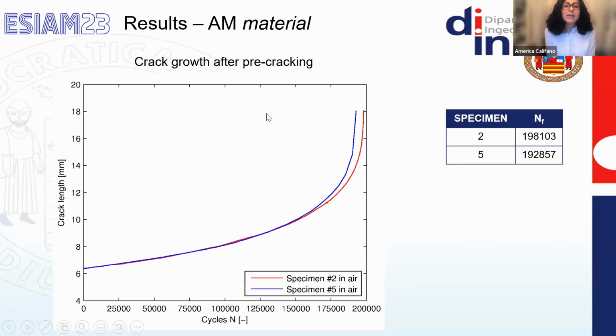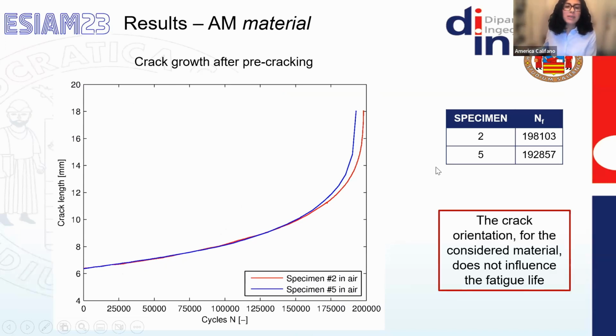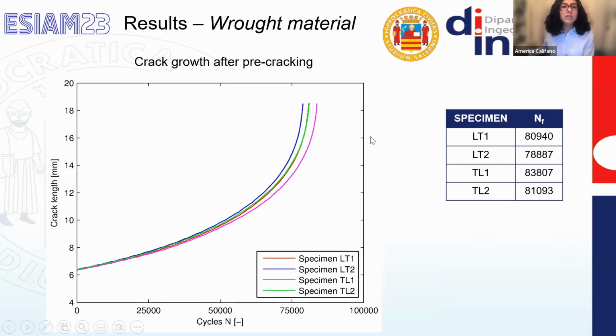At this point, we can take a look at the crack growth curves after pre-cracking for the 2 different sets of specimens. For the additively manufactured CT specimens shown in this slide, we can see that the 2 curves for specimen number 2 and number 5 are almost completely overlapping, and even in terms of the number of cycles to failure, the specimens share a similar behavior. So there is no influence in this case of the crack orientation on the fatigue life, and a similar behavior can be found in the wrought material. If we take a look at the 4 crack growth curves after pre-cracking, they share similar behavior, and the numbers of cycles to failure are quite similar to each other.